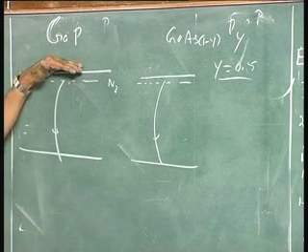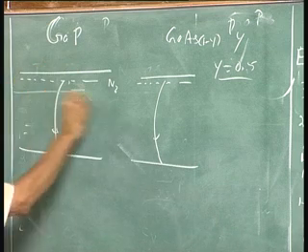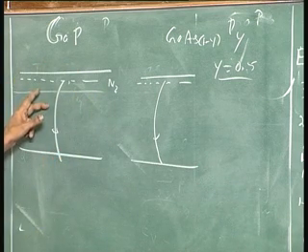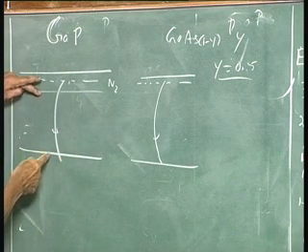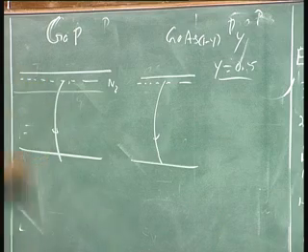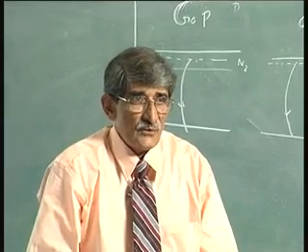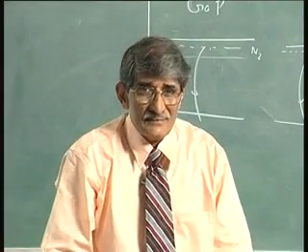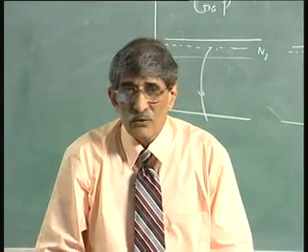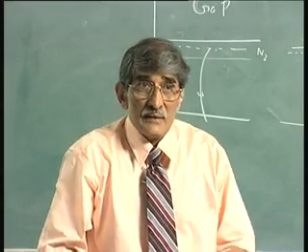If I introduce some other impurity, that will introduce a level there, zinc oxide, the energy will be reduced, the wavelength will go up, and we can force it to red light. 2.26 minus 0.3, that is the band gap transition. So, that is the thing.